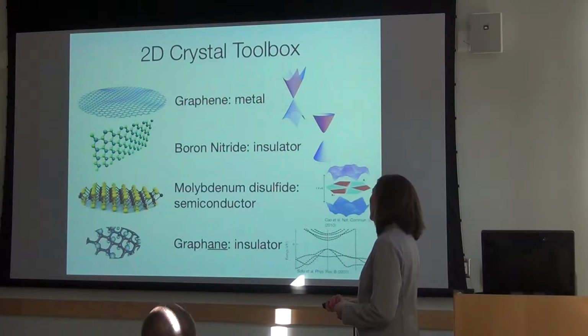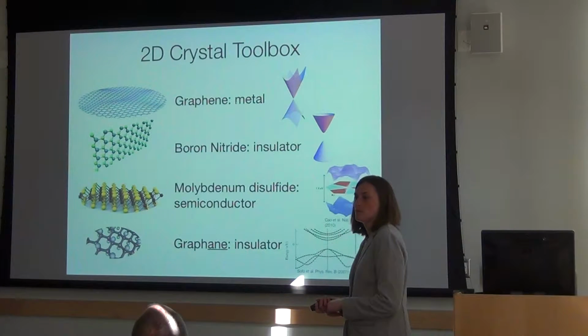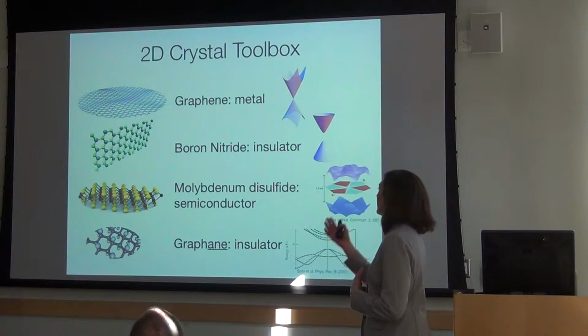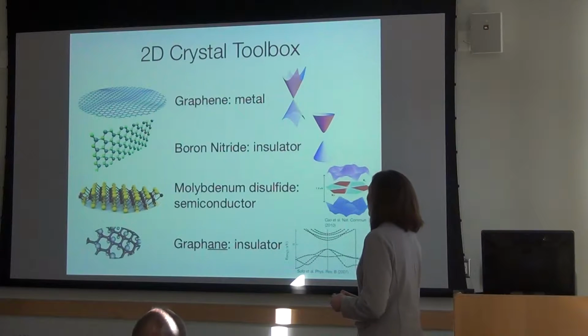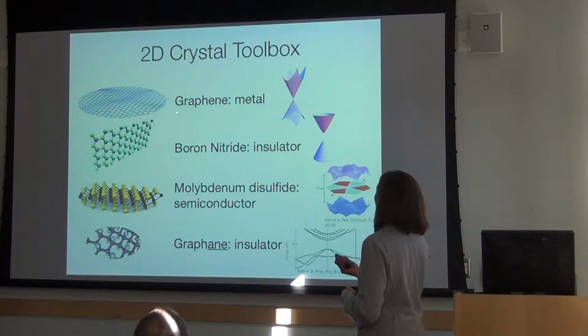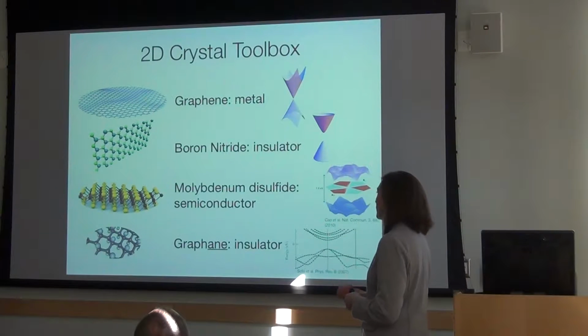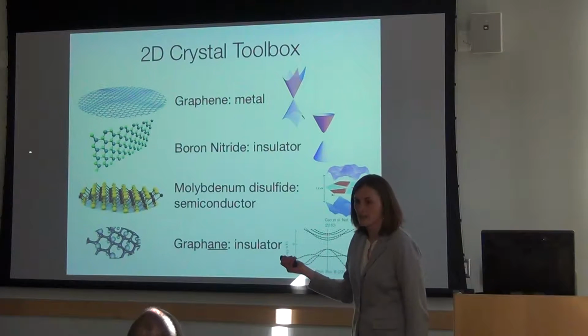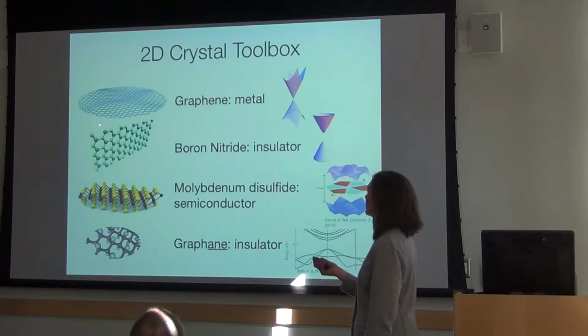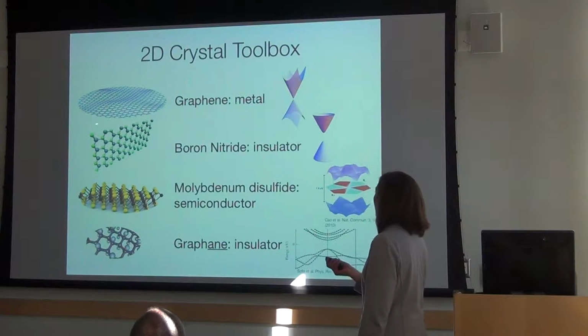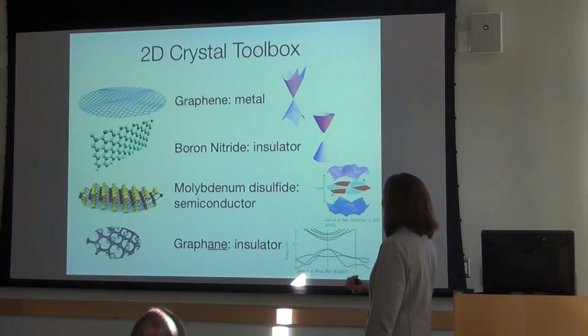Okay, so this is our 2D crystal toolbox. Of the library of two-dimensional crystals, we can access metals, something that acts more or less like a metal. Boron nitride, which has the same crystal structure as graphene, except that the atoms in the lattice are alternating boron and nitrogen. And this breaks a symmetry and makes this material into an insulator, a pretty wide bandgap insulator.